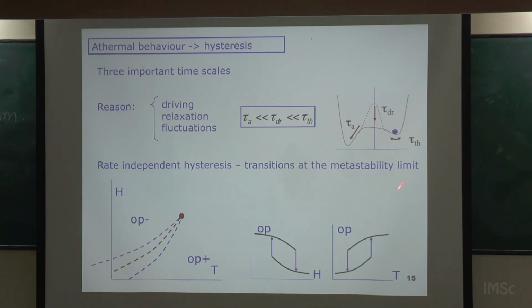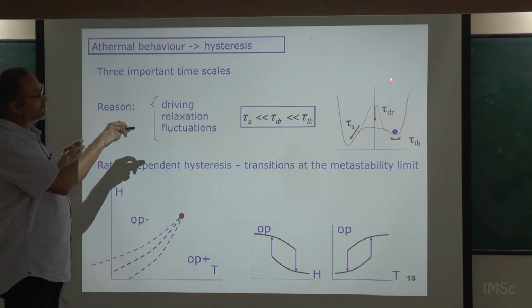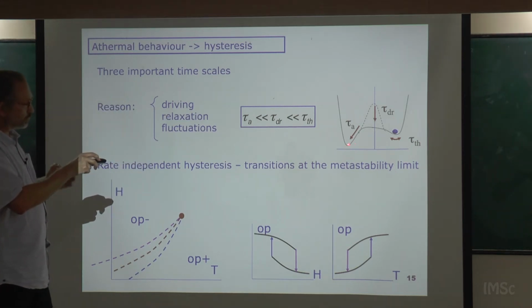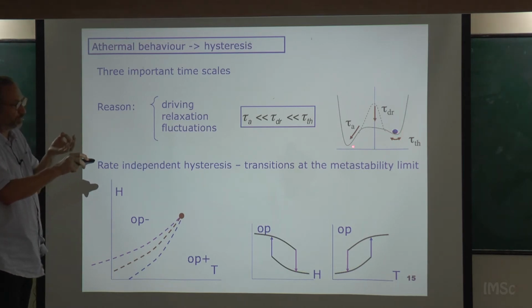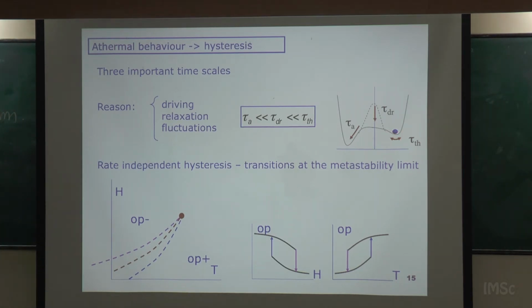How do we understand that? Imagine this double well that I plotted before. You were in this well, which was the best one first, and then suddenly you change the field, and the system has to jump from here to there because this is lower free energy. How does the system change from here to here? There are three time scales to be considered here. One is what we call the typical thermal relaxation time scale. The system, given that there is a certain temperature, is fluctuating in this well with a typical time, tau thermal.